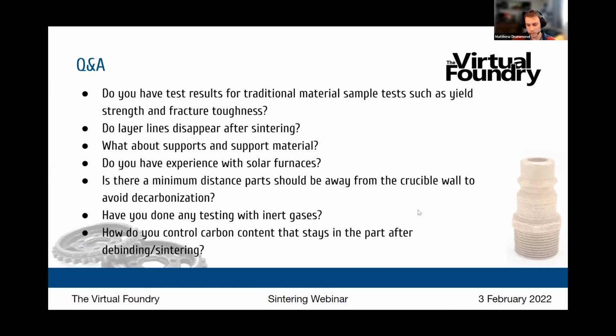But to actually deal with decarbonization, inert gas is great. Of like a furnace that you can put an inert gas through, it is wonderful. But just having enough carbon, where the carbon will get taken away from the sintering carbon on the top, or extra carbon you've put within the furnace. Because once that's gone, then it's going to start taking from your part. Because the part's the hardest to get. It's all the way down in the bottom of the crucible. But if you have enough carbon in other places that it can take from before it gets to your part,